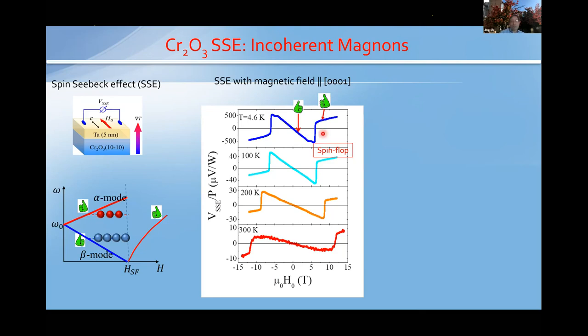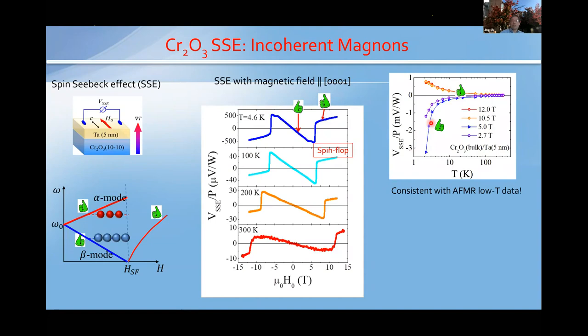But if we decrease the temperature, we decrease the alpha mode, which is the right-hand mode population, right? So that means the contribution from right-hand helicity is getting smaller and smaller at lower temperature. And eventually when we pass this point, the temperature is low enough that essentially all the magnons are left-hand magnons. This caused this rapid increase in the magnitude of the left-hand contribution of the incoherent magnon contribution detected by spin Seebeck. I showed you this slide earlier.